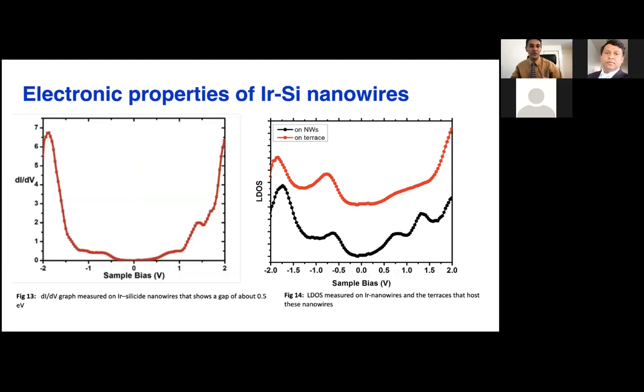Then we moved on to the electronic properties. So we did dI/dV versus the sample bias. Then we found that these nanowires are semiconductors. You can see that around the Fermi level, there's a flat region. The flat region means there's a band gap. There's an opening up of a band gap. The size of the band gap is around 0.5 electron volts.